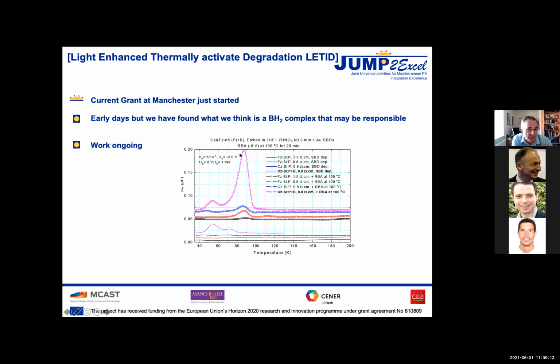And this complex's formation and dissociation is very complicated. We've already seen that from the DLTS data we have. So we're looking into it to see if it could be correlating with LeTID and whether it's responsible. Basically, it's a donor. So what happens is you create a deep donor, which is damaging to the minority carrier lifetime under certain circumstances.